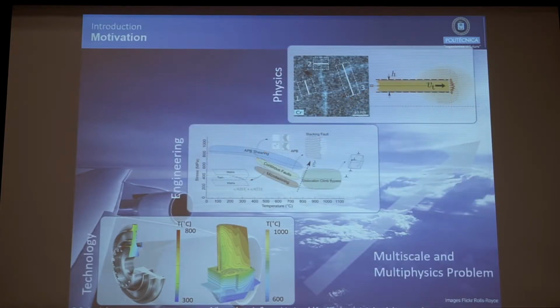And if you have a look here at the deformation map, as you are increasing the temperature, there are new deformation mechanisms that are appearing that were not the target in the past for research because we were not in this temperature regime, but now they are critical because we are getting in service in this temperature regime. These deformation mechanisms are really complex because they couple diffusional processes, so chemical changes, with standard plasticity, dislocation shearing. And among them, the most important one is the microtwin mechanism, which I'm going to explain next.